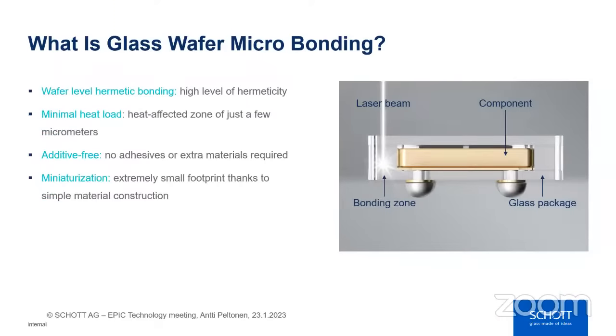But we have developed a laser-assisted process called glass microbonding, which allows you to bond glass layers not from the surface, but only at the interface. We do not add anything in between the layers, so there's just one biocompatible material in contact with the body, which is the glass. The bond between the layers is achieved with such high precision that the heat affected zone is just some micrometers, so inside the cavity the temperature remains at room temperature, and we don't risk damaging even the most sensitive components that need to be encapsulated inside the glass.